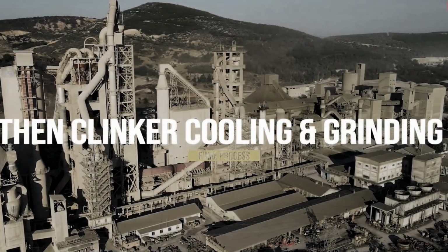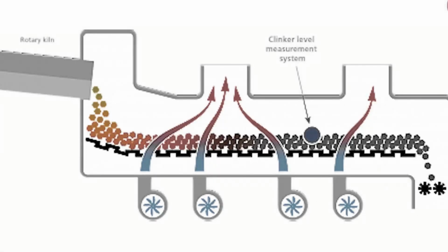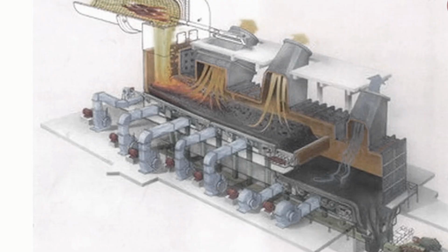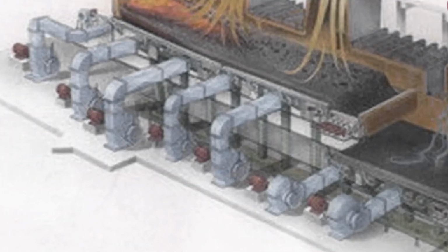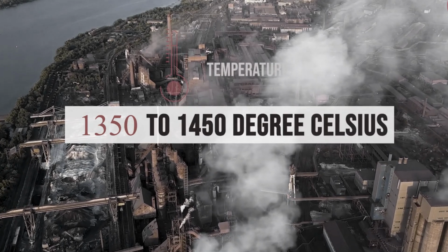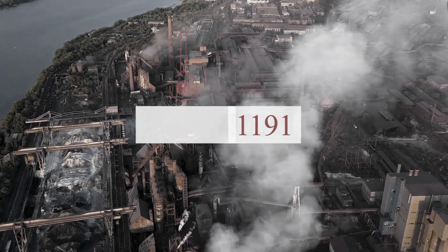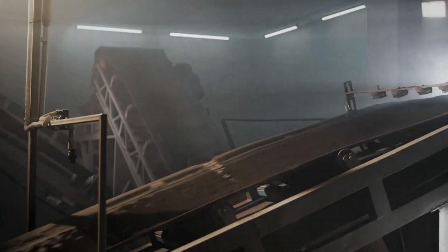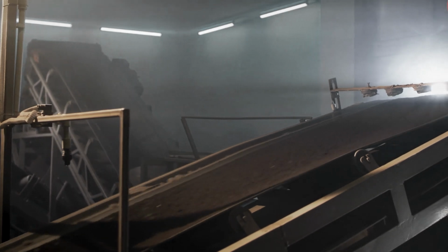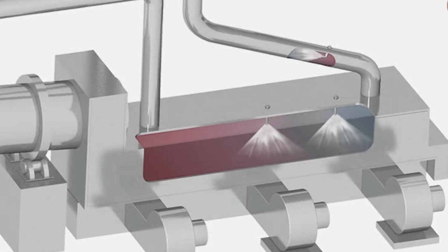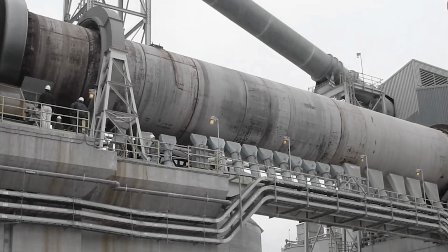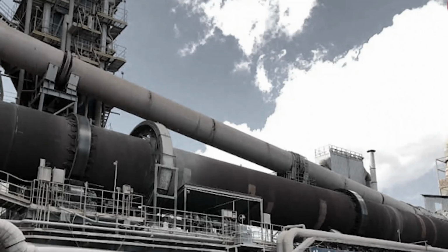Then comes the clinker cooling and final grinding process. The hot clinker discharged from the rotary kiln is cooled in the grate cooler by forced air, which is extracted from the outer atmosphere by grate cooling fans. The temperature of the clinker after being cooled drops from 1350 to 1450 degrees Celsius to around 120 degrees Celsius. The cooled clinker is then transported to clinker silos or hoppers directly by conveyors for storage, and later the cement grinding process. The hot air in the cooler is recirculated back to the rotary kiln for reuse, which further saves the energy consumption of the cement plant.